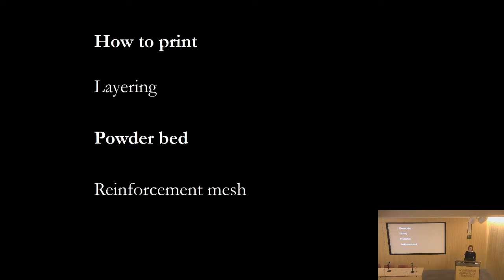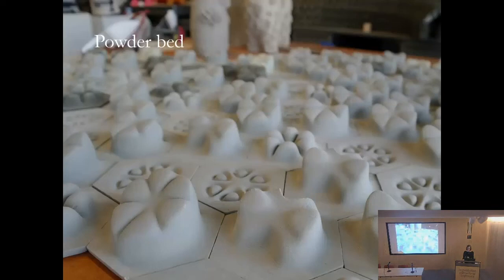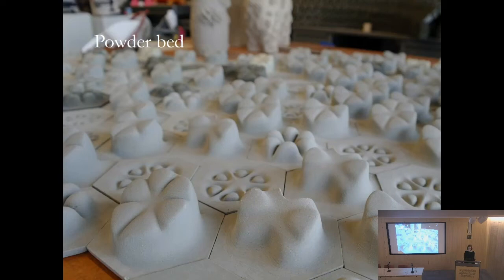The second method is the powder bed. You can use grain sizes from a tiny powder up to five-millimetre thick grains, using a resin — either chemical or just a binder material. You layer the powder, place the resin where you want the final elements to be, then remove the excess powder. These planters for a green wall were produced with a cement and polymer mix on a very old 3D printer — yet you can still produce amazing things.